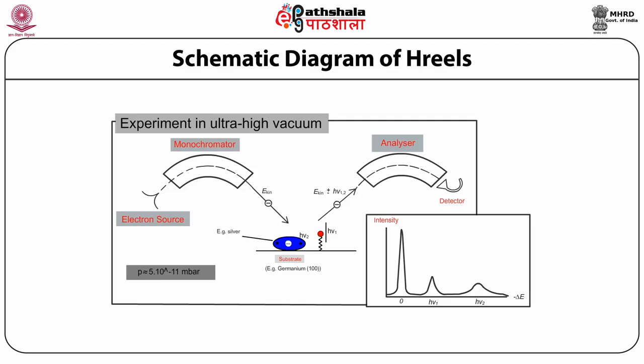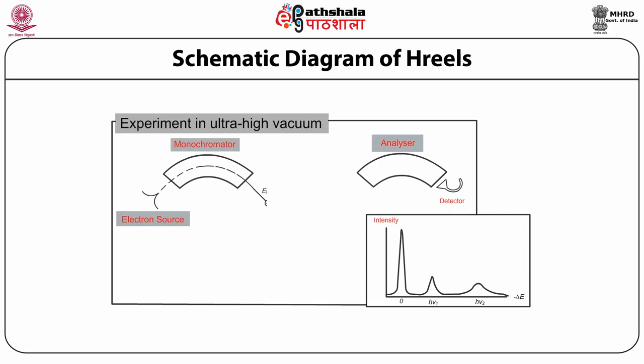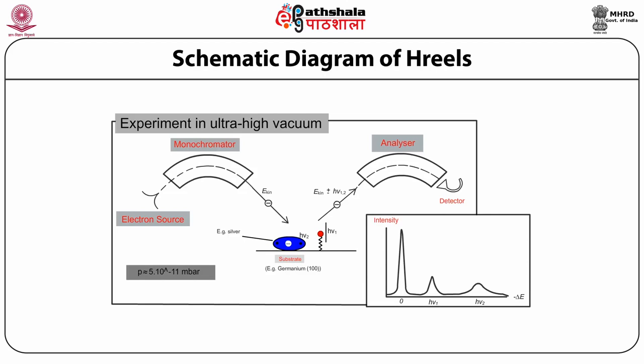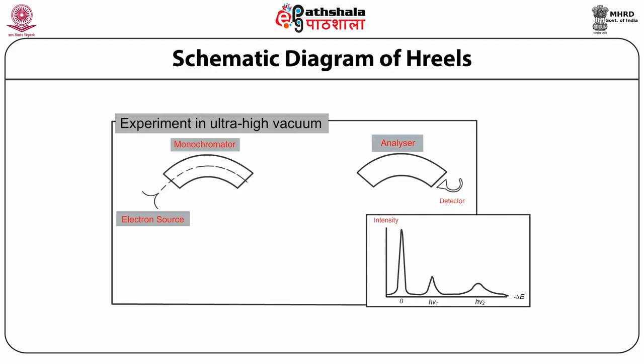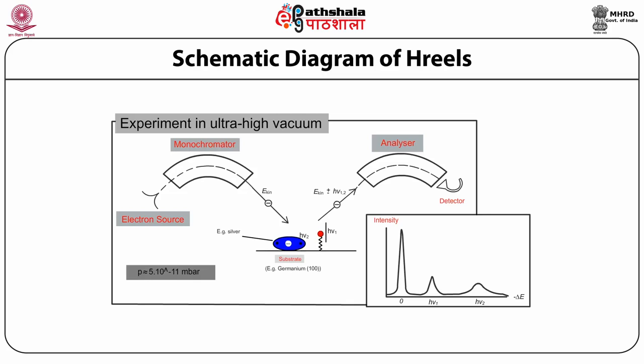The electron source is a filament tip which emits electrons with a thermal distribution of some 100 milli electron volts. With the monochromator, it is possible to lower this distribution to about 3 milli electron volts, in modern spectrometers about 0.5 milli electron volts. The electrons are then scattered at the sample surface. Some of them are scattered inelastically, which results in a change in their kinetic energy, and the momentum as well changes when we are measuring the kinetic energy.